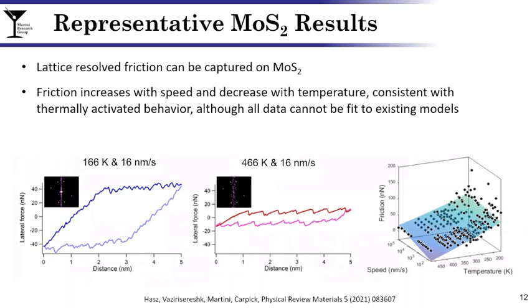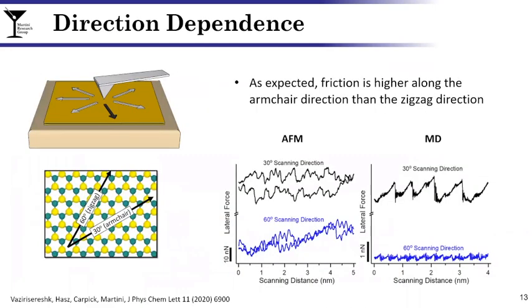But to get back to something fundamental, again, correlating friction to atomic features, we did a study focused on the direction dependence of sliding. Shown on the left, in the lower left image, is a schematic of the topmost layer of MoS2. And what you can see is that conceptually speaking, there are two directions that you might be able to slide that would give you very different friction.